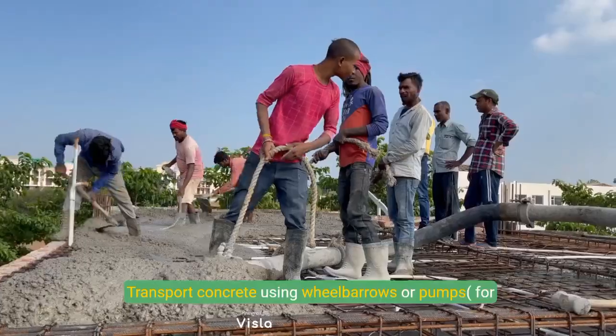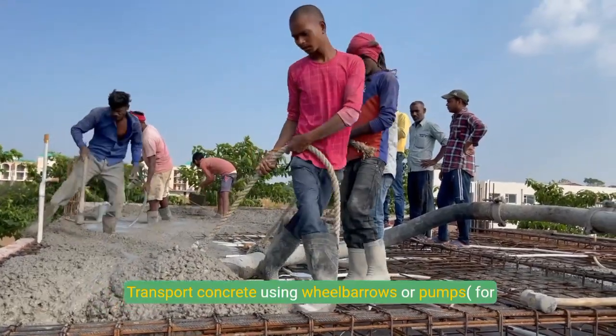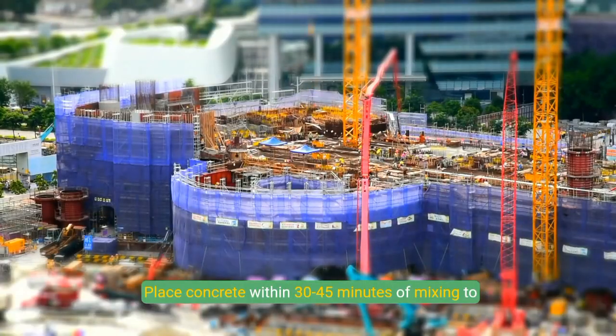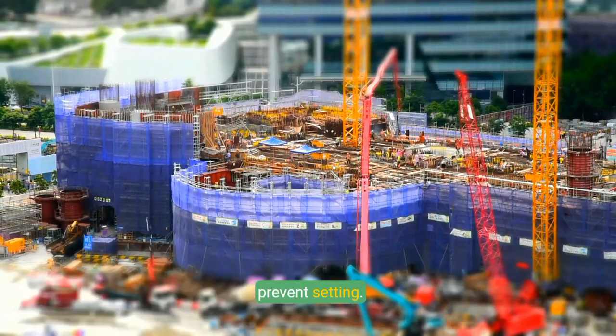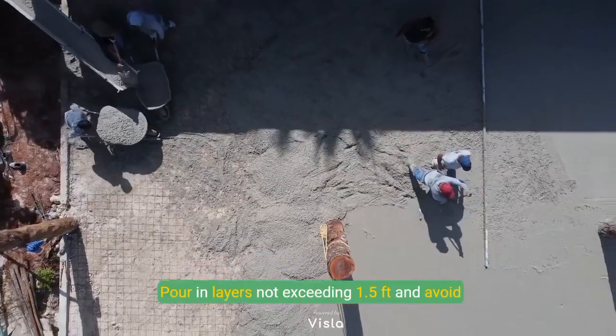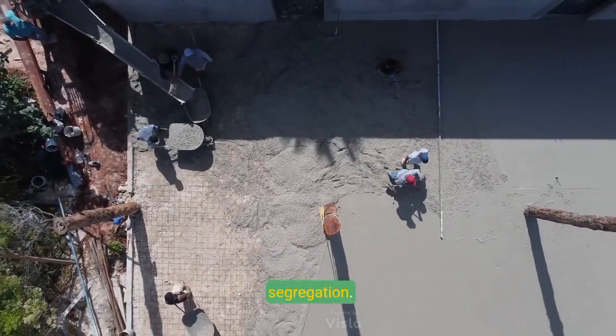D. Transportation and placing. Transport concrete using wheelbarrows or pumps for large projects. Place concrete within 30 to 45 minutes of mixing to prevent setting. Pour in layers not exceeding 1.5 feet and avoid segregation.